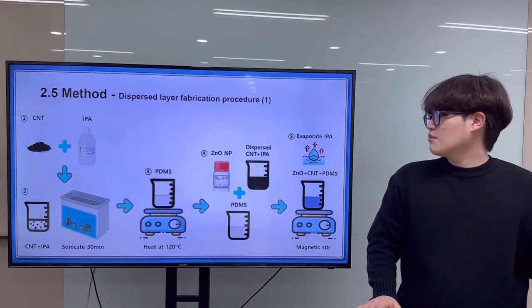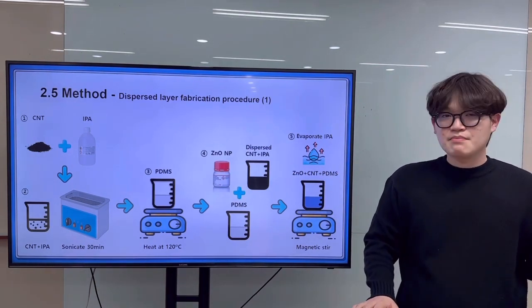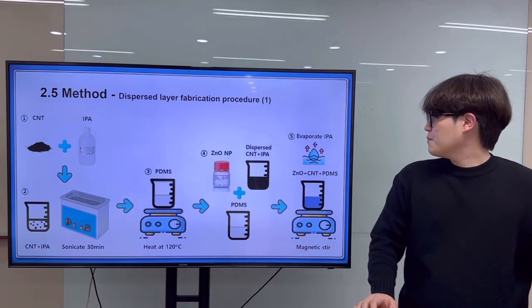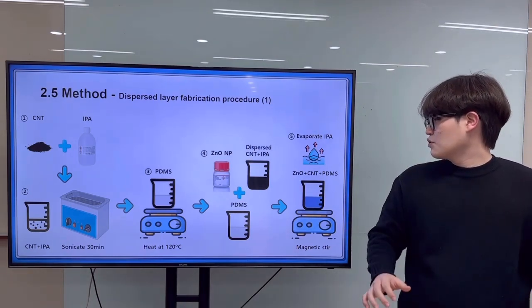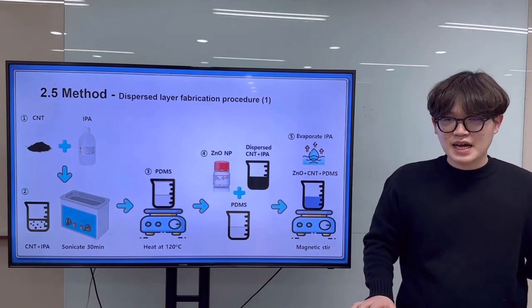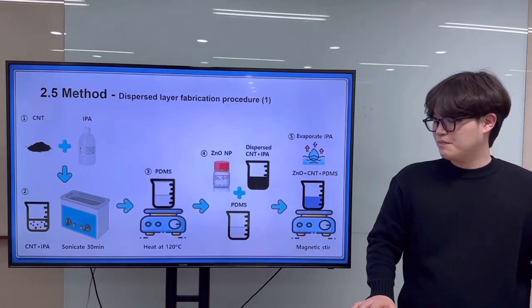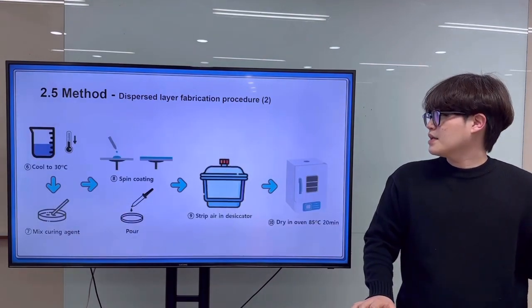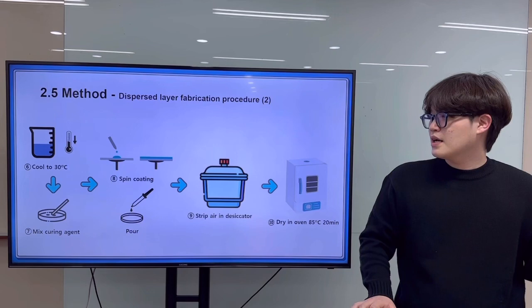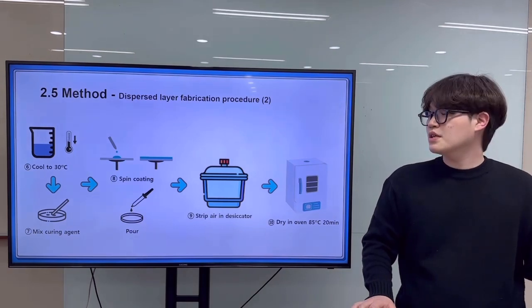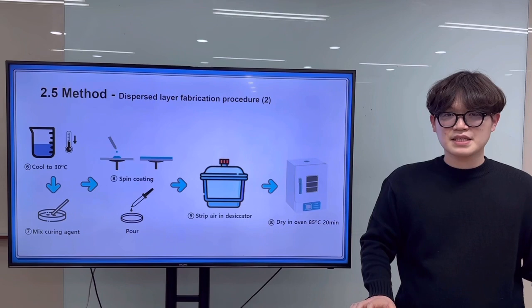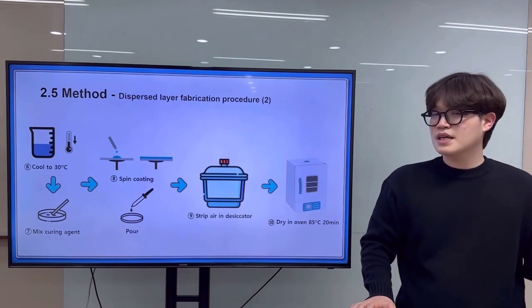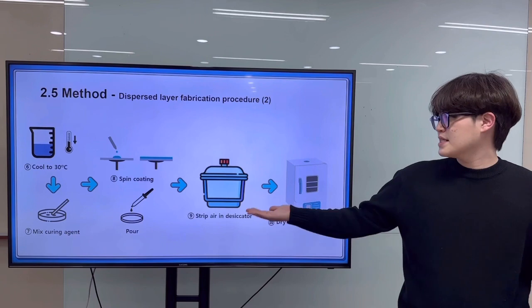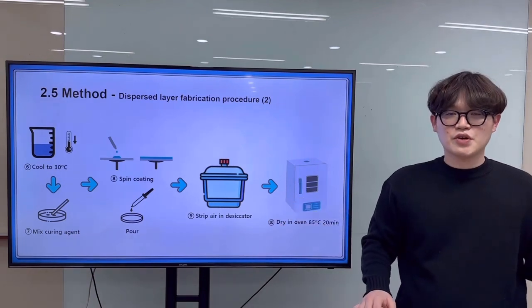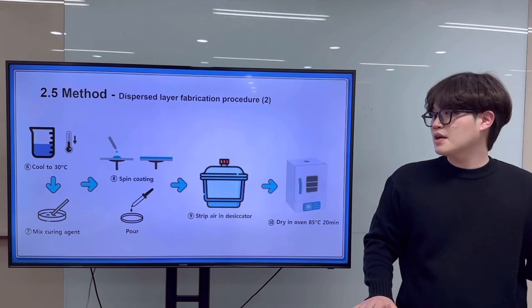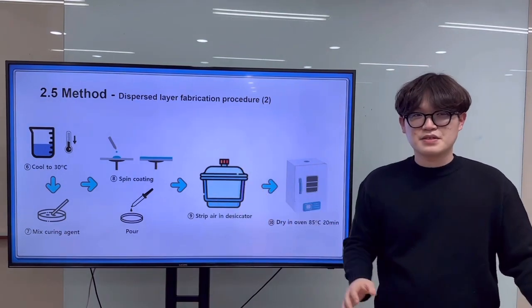And then we stir with a magnetic stirrer for mixing the solution and evaporating IPA for an hour. Next, cool down the solution for 5 minutes down to 30 degrees. The subsequent process is the same as the PDMS curing procedure except for the spin coating method.